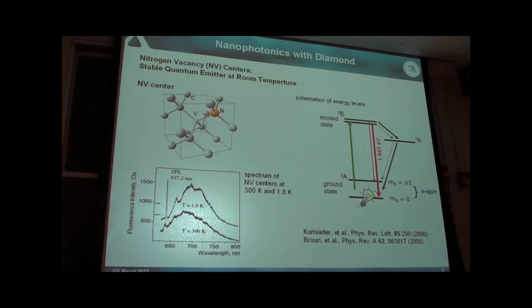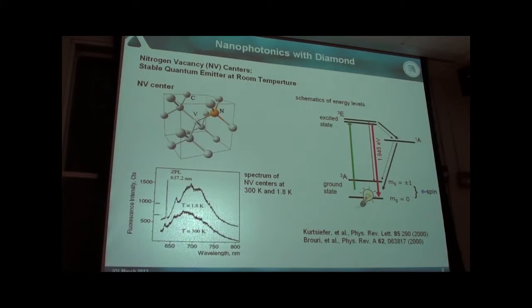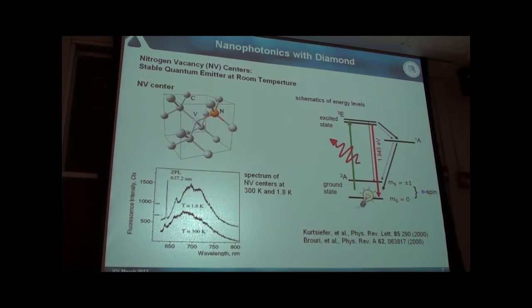It's optically stable forever, even at the single defect center level. There is a ground state and an excited state — a triplet ground state and a triplet excited state. For optical properties, you excite it off-resonance with a green laser, relaxation brings the excitation to the excited state, and after some tens of nanoseconds you have spontaneous decay, giving you a single photon. So it's a straightforward single photon source emitting in the red spectral range. There are some intermediate states, and sometimes excitation can escape via these, leading to some blinking — the single photon source goes off sometimes, seen as interrupted emission in correlations.